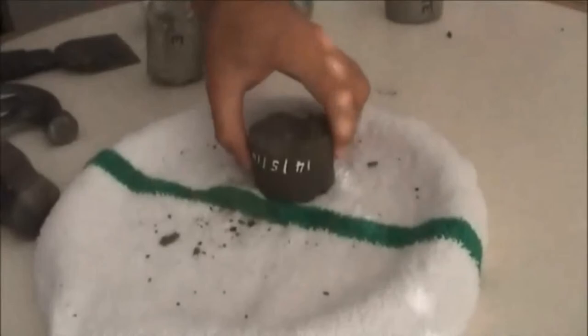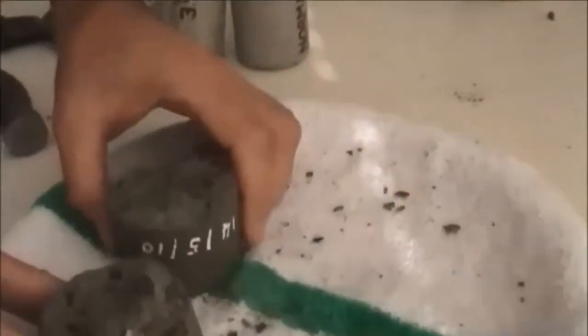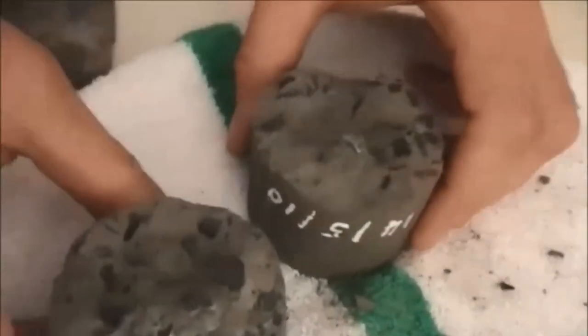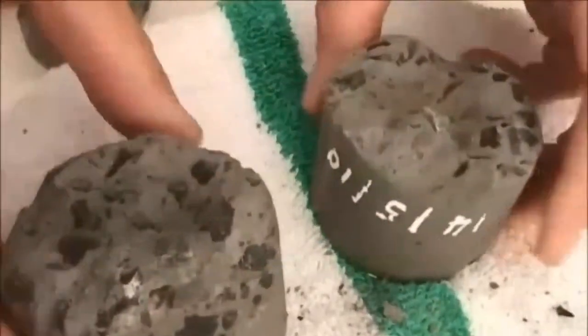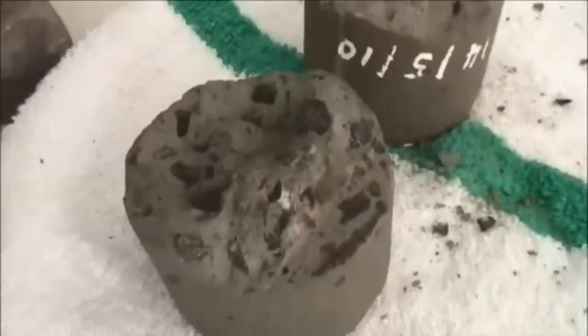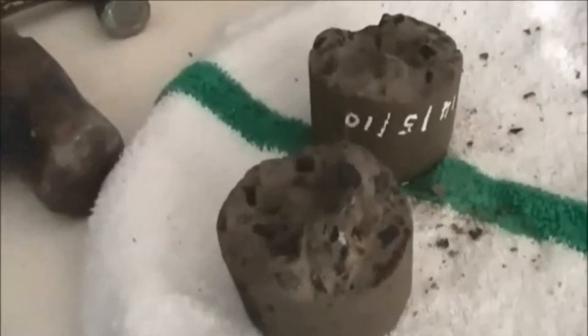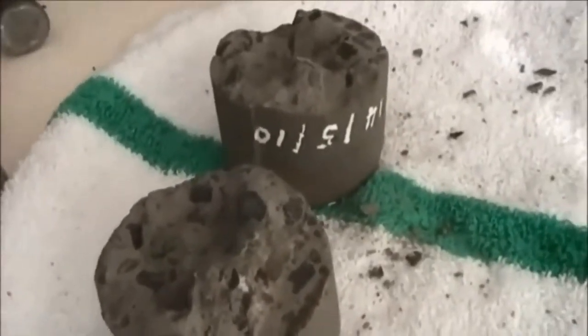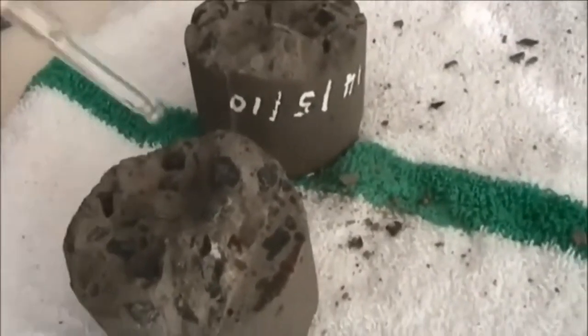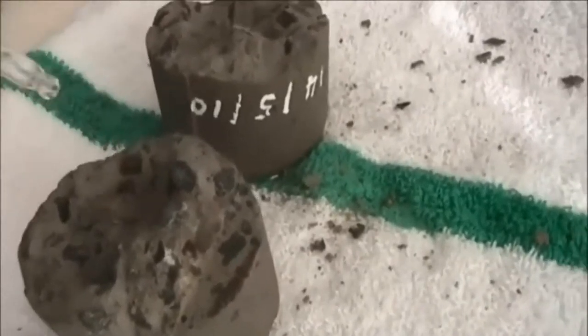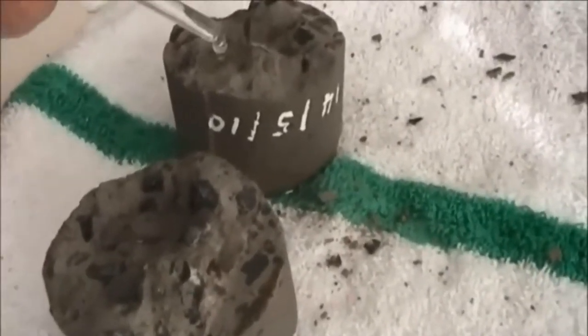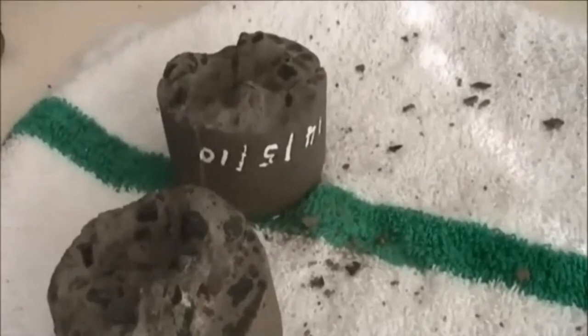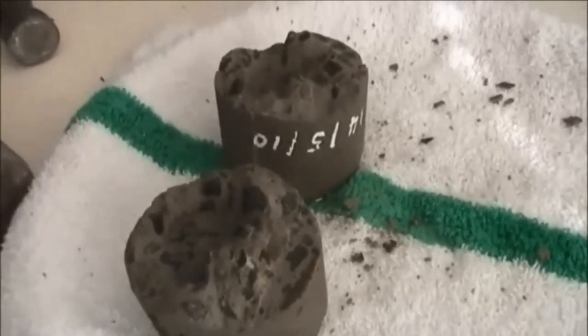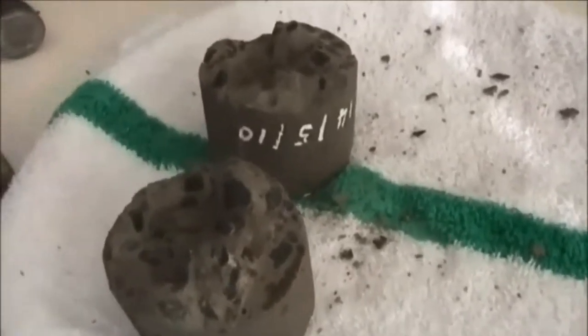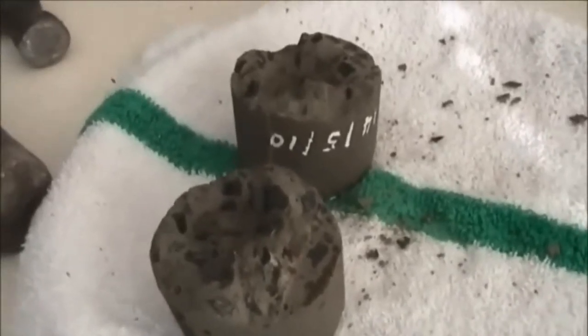Just retrieving the sample there, and you can see there's absolutely no difference in the colour between the outside and the inside. It is completely saturated. That is so-called water repellent concrete. It passed all the tests in the laboratory, a 30-minute test, but you can see if you put water on it, it's immediately saturated. You are actually looking at permeability, because that concrete is fully saturated now.